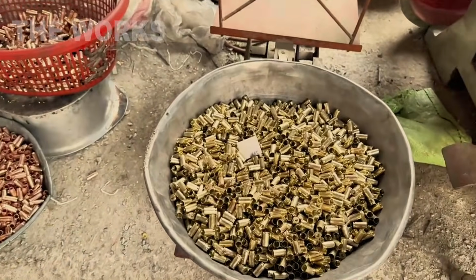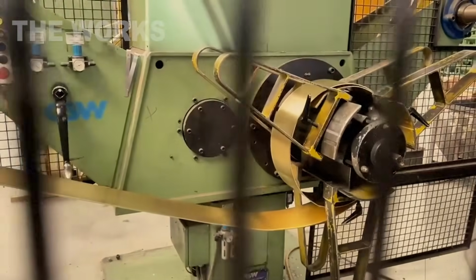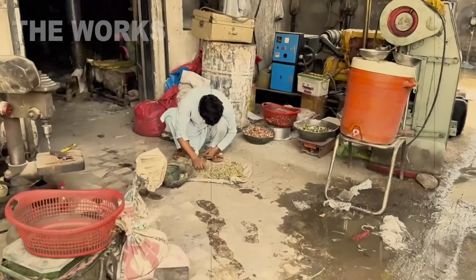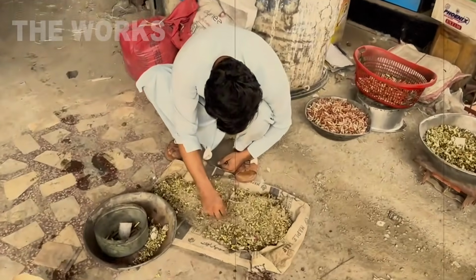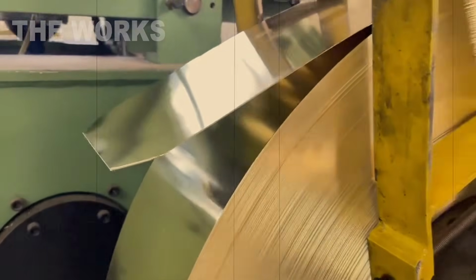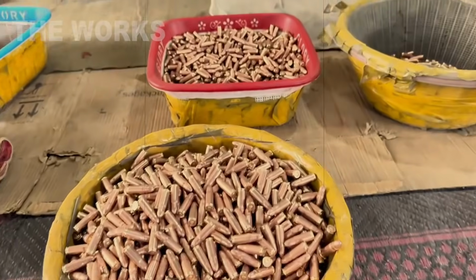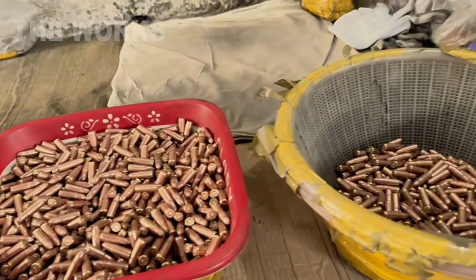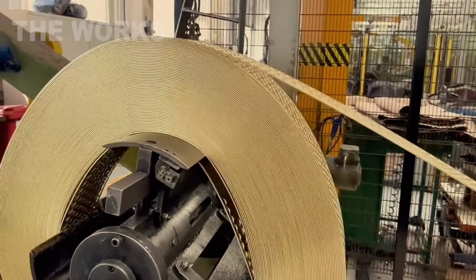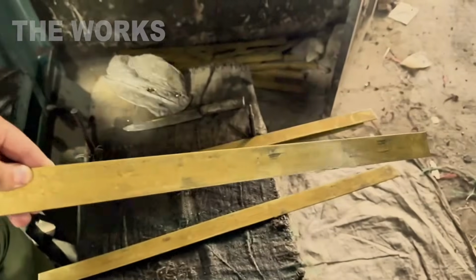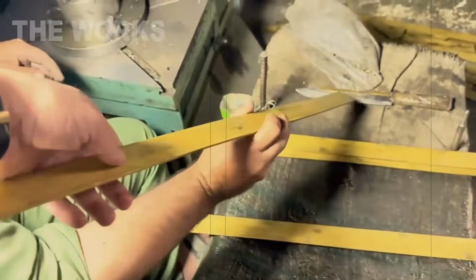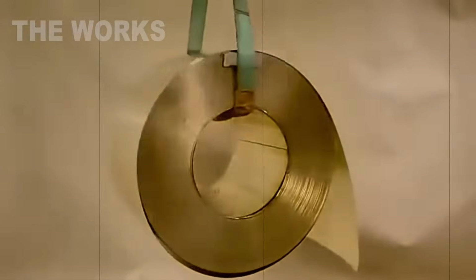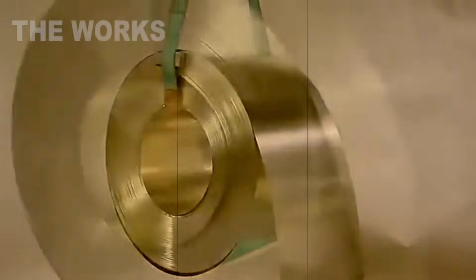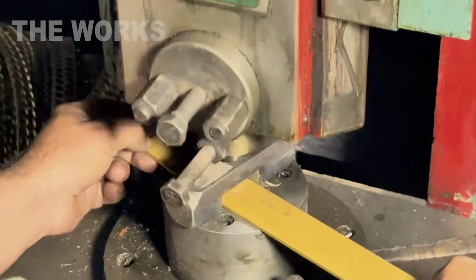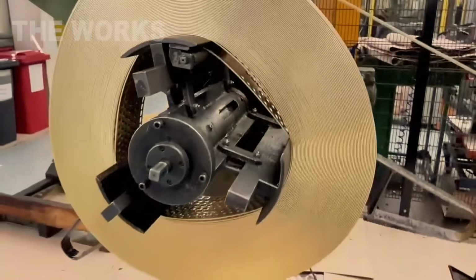Hundreds of millions of cartridges roll off factory production lines worldwide every year, and each one passes through quality control with micron-level precision. The primary material is brass, an alloy of 70% copper and 30% zinc. It's ordered in massive coils roughly 1.5 millimeters thick, weighing up to 2,700 kilograms. These coils are supplied by metallurgical plants. Upon arrival at the factory, the brass is unwound on a special platform and fed into a rolling mill. The metal's temperature at this stage reaches 315 degrees Celsius to make it more malleable.